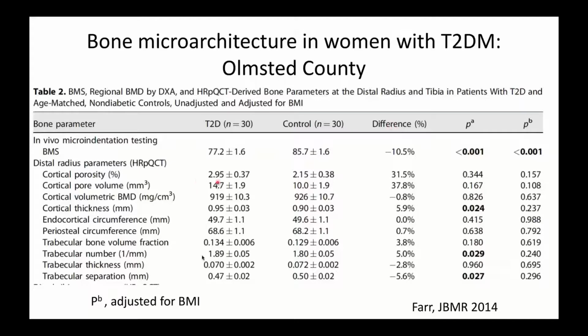And what I want to point out first here is that, and you see that every study is concordant for that, there is no evidence of a deficit in the trabecular network in diabetics. The trabecular bone volume fraction, number, thickness is not worse than in control. Actually, some parameters are slightly better, like trabecular number here is better. Now, for cortex, there is in this study no significant differences really, besides a thicker cortex. So more trabeculae, thicker cortex, so better bones in these type 2 diabetic patients, okay?